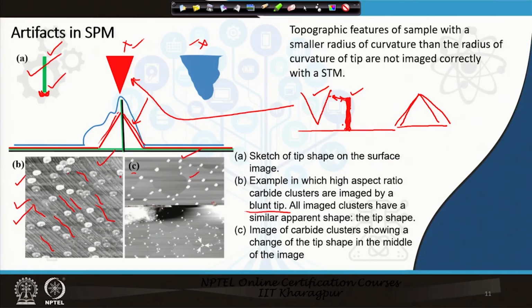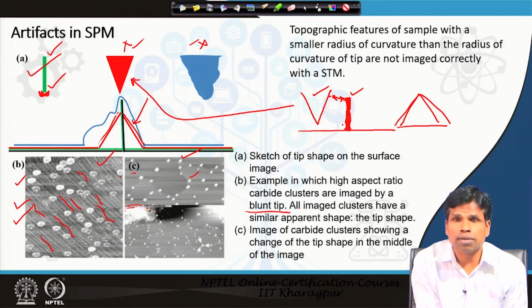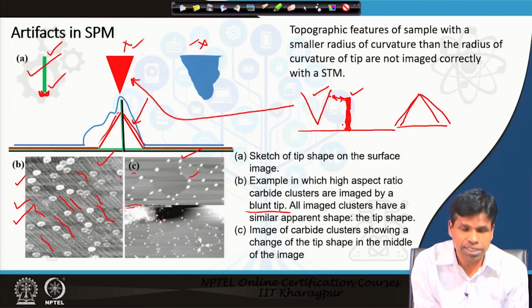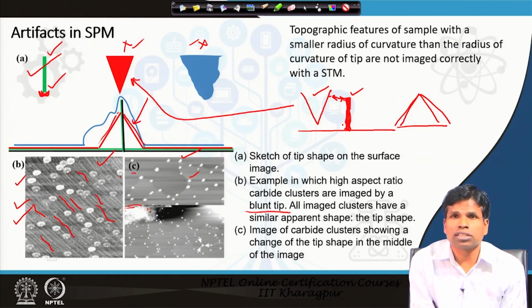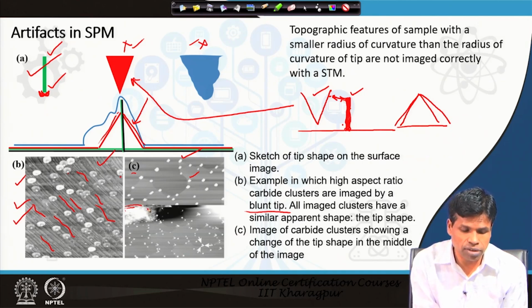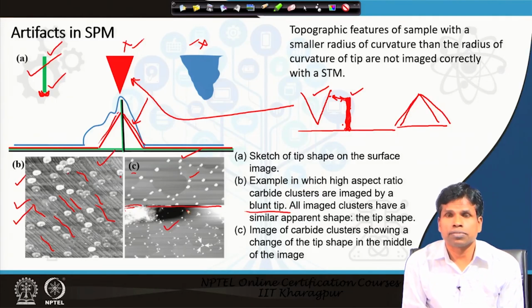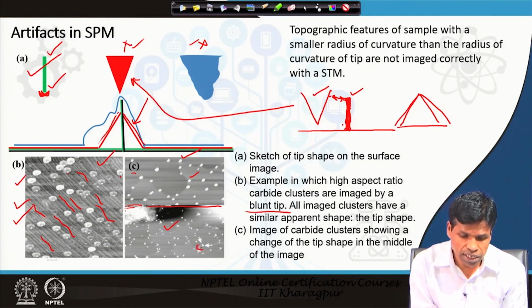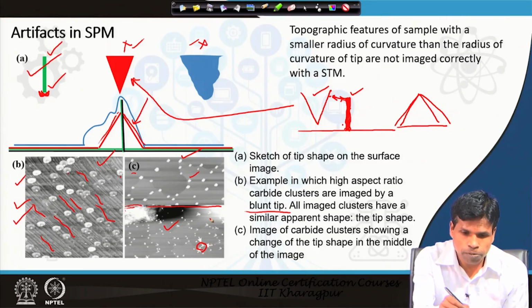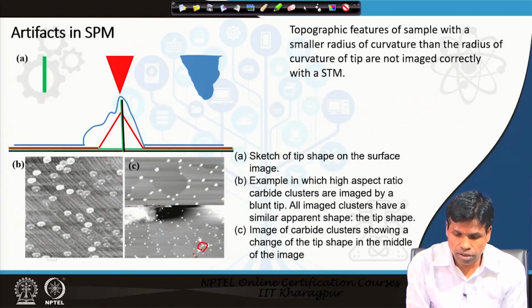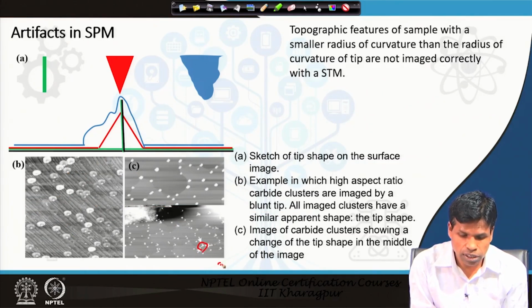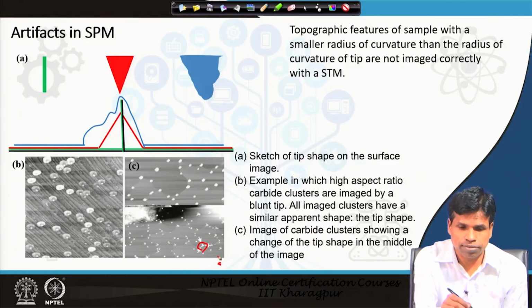In the C image, you could see clusters of completely different shape. Here it is larger, and during the scanning we see that in some places the tip touches the sample. There is a contact between the tip and sample, and thereby a change in the tip shape. When the tip scratches the sample surface, the tip shape changes, and that is what happened. After the tip shape changes, you see a completely different type of features, and this is again not correct, because some of the particles appear as a triangle or something like three dots. So, those are not correct; this is due to artifacts.